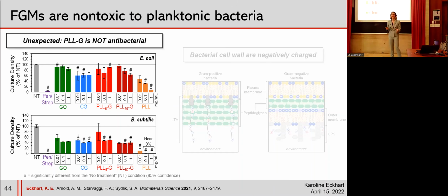And this was surprising because PLL on its own, just the free polypeptide, is toxic to bacterial cells. We can see a large reduction in culture density when treated with the PLL control material. So with this result, we hypothesized that the PLLG, because it has a peptide that's immobilized on the surface, isn't able to insert itself into the cell walls of the bacteria as readily and cause cell death. And so now we're looking at some materials with tunable surface charge. They're not toxic to bacteria. How can we investigate these materials as a way to control bacterial adhesion without sacrificing the viability?